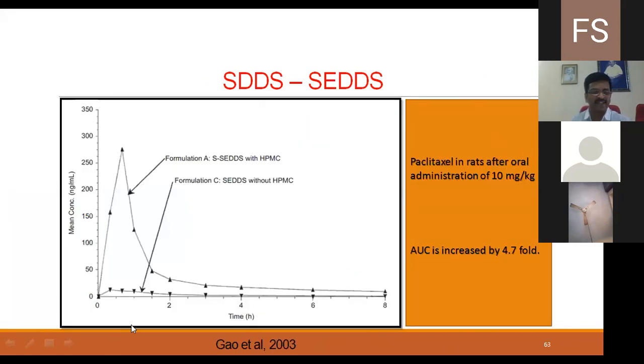And when the same paclitaxel was given for in vivo studies in rats at the dose of 10 mg per kg body weight, without HPMC, the line is very near to the x-axis. But when it is prepared in the SEDDS form with HPMC, we could see the spring effect and also the parachute effect, for a sufficiently good period. For 2 hours, it is the maximum effect, and afterwards it is sustained up to 8 hours. Even at 8 hours, there is an increase. And if you observe the total increase in the AUC, it is increased by 4.7 folds.